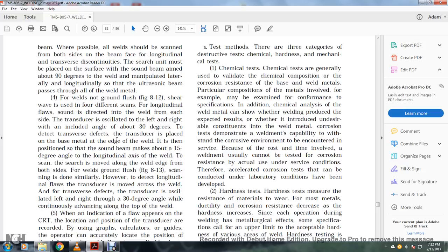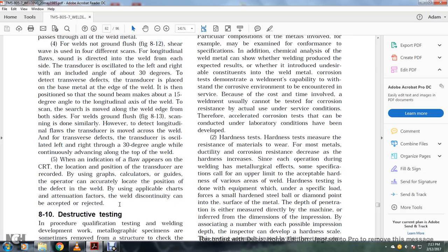The transducer is placed on the base metal. The edge of the weld is then positioned so that the sound beam makes a 15-degree angle to the longitudinal axis of the weld, and the search unit moves along the weld edge on both sides of the weld for ground flush welds. The scanning is done similarly; however, to detect longitudinal flaws the transducer moves across the weld, and for transverse defects the transducer is oscillated left to right through a 30-degree angle while continuously advancing along the top of the weld. Five.